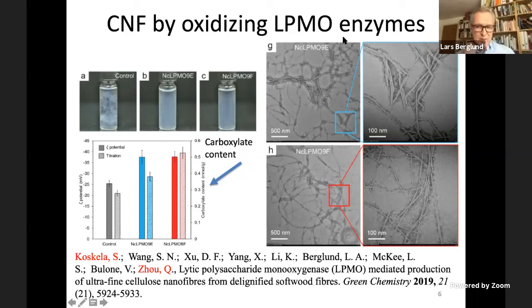We have used enzymes previously, endoglucanases, for pre-treatment of fibers of chemical pulp to facilitate fibrillation. But here the idea is different. The LPMO enzymes are actually able to oxidize cellulose. So they create carboxyls by cutting the cellulose chain and oxidizing the end.